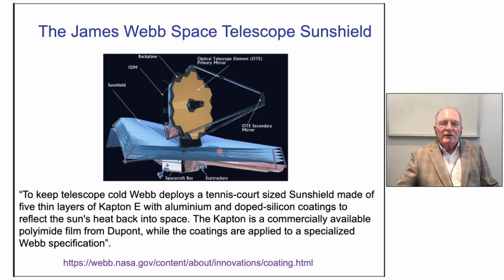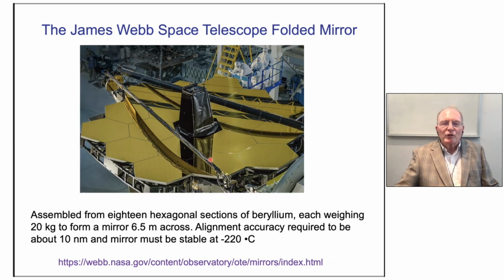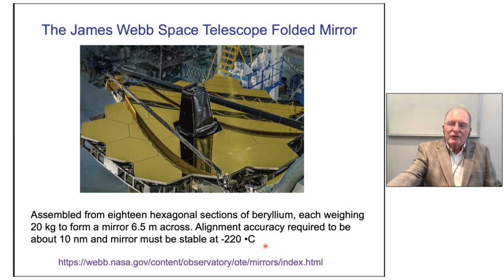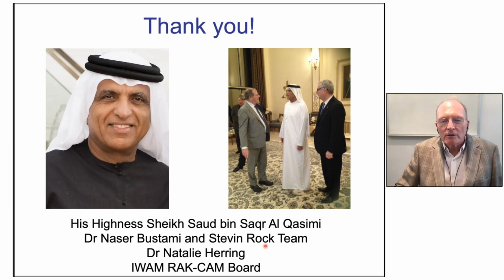And this Kapton 5-layer aluminium and doped silicon coating keeps the heat away from this, even at the very low temperatures in outer space. And the telescope is made of beryllium coating, which had to be folded up into 18 sections to get into the rocket, and is now unfolded as planned in the solar orbit, and has to be stable at -220. So I'm skipping through that because I know my time is up.